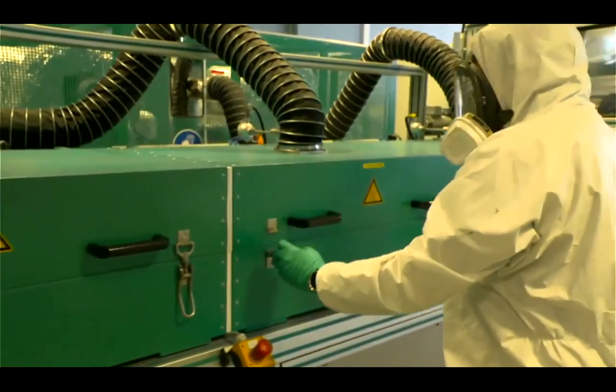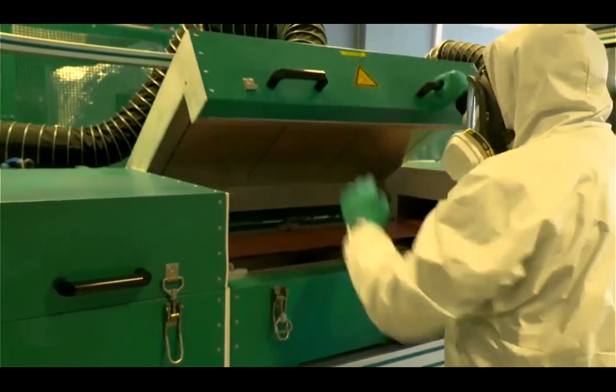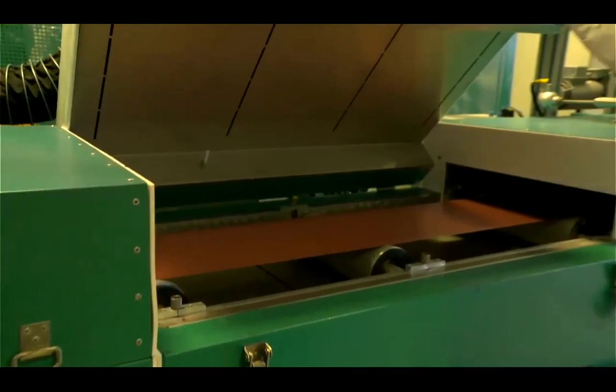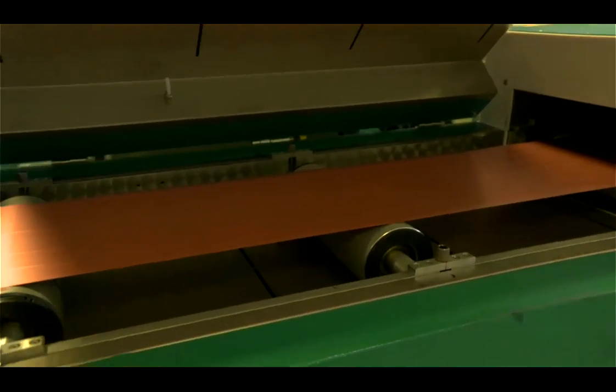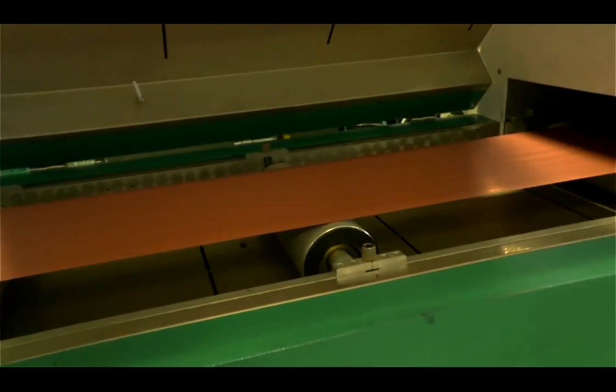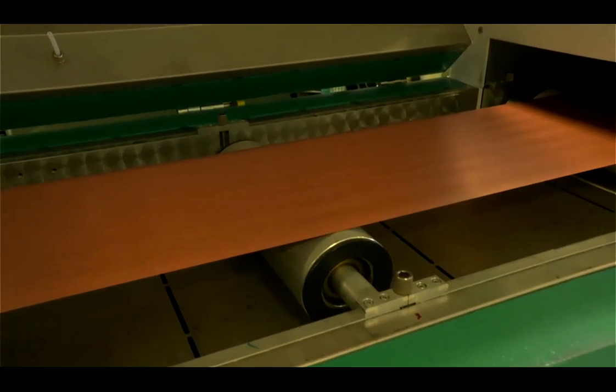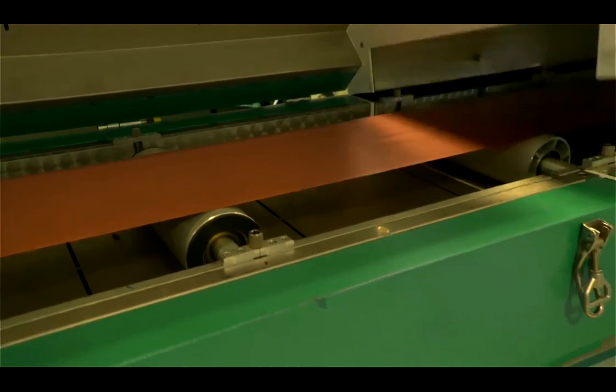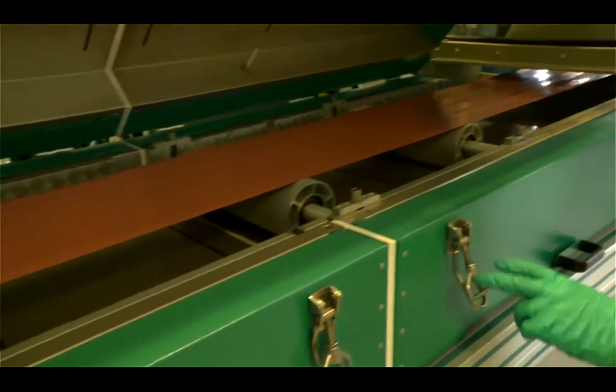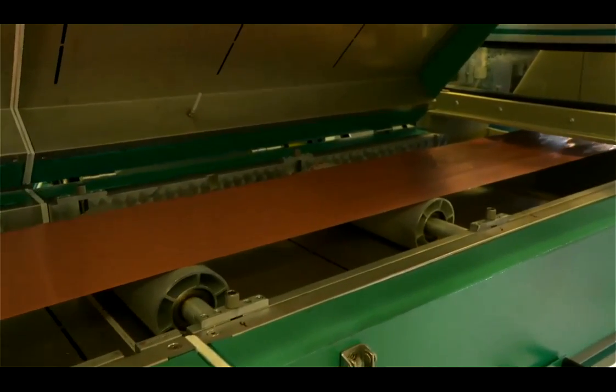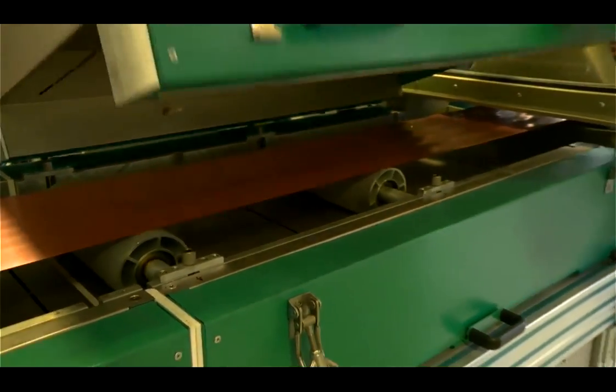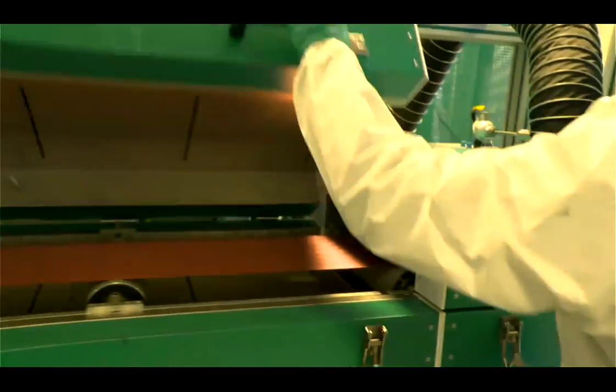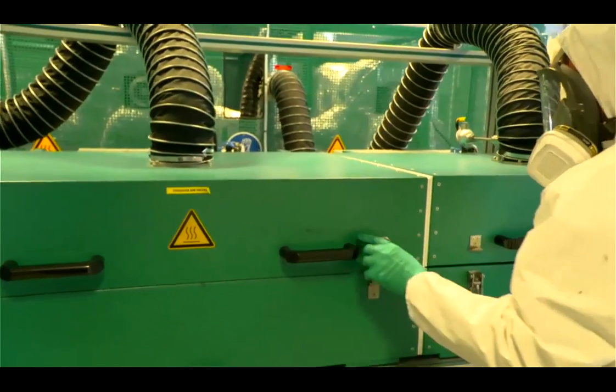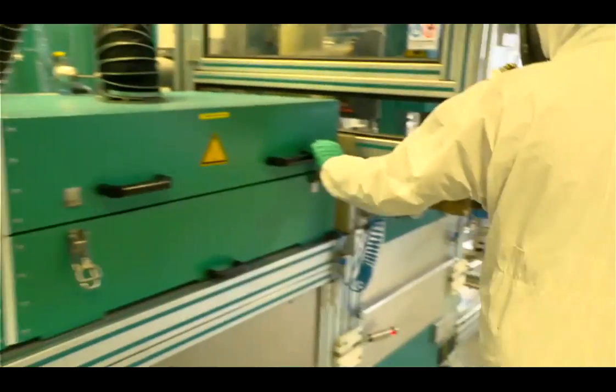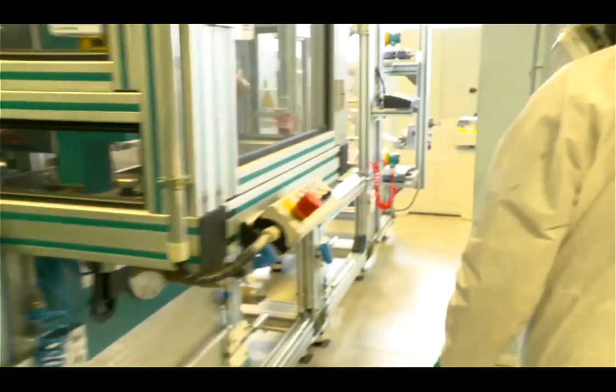Because as I mentioned in my speech before, we cannot increase the temperature as much as we want, because this increase in temperature will provoke the migration of the binder. So we need to control, there is a balance between controlling the structure of the electrode and making sure that we are removing the water or the NMP, or whatever the solvent is in the electrode.